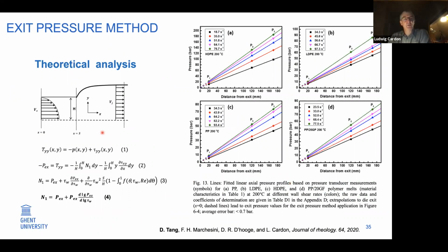So you see here also, briefly explained, the velocity profile of a material. When you push it through your extruder and your die, the inside velocity is high. At the wall itself, we have a velocity of 0. Due to that effect, you create finally your die swell, due to the induced pressure. And then finally, at the end, when you don't have any more the die swell, or when the die swell pressure has occurred, we have a uniform, straightforward flow of velocity of our material.